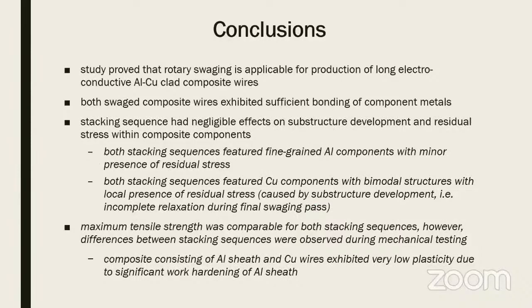As a conclusion, I would like to say that this study proved that the rotary swaging technology is well applicable for production of long electroconductive aluminum-copper clad composite wires. As we saw, both the swaged composite wires exhibited sufficient bonding of the component metals. We also saw that stacking sequence had negligible effects on substructure development and residual stress.